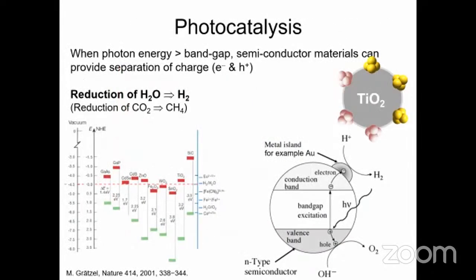For the photocatalyst, the other groups actually in University of Adelaide, they have done some of the photocatalytic reaction, especially by using it for the hydrogen production and for the water splitting to produce the hydrogen. And this is the phenomenon where we deposit the gold on the top of the oxide surface to increase the catalytic reaction and to have this kind of exchange on the top of the metal core to do the catalytic reaction by the reduction of the water itself and producing the hydrogen. And also for the reduction of the CO2 emission and to get the methane itself.